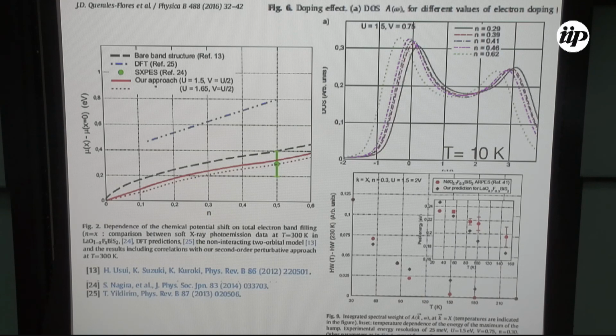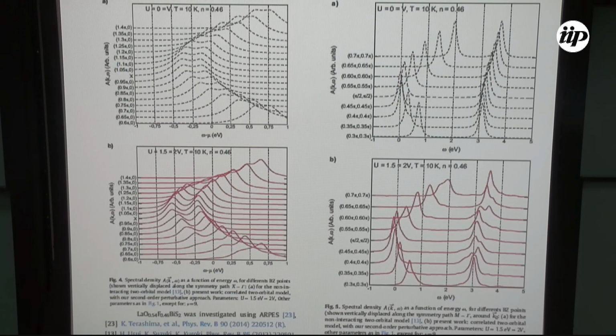And then we did predictions for the density of states as a function of doping. Well, this is something else I will not enter into now. These are the kind of results we get for the spectral density function along different lines. This is near point X of the Fermi surface, X and gamma path. And this is the effect on the Usui bands without correlations, and this is with a second order approach, which when we compare with Terashima's ARPES results, these red results describe much better what is really found there.